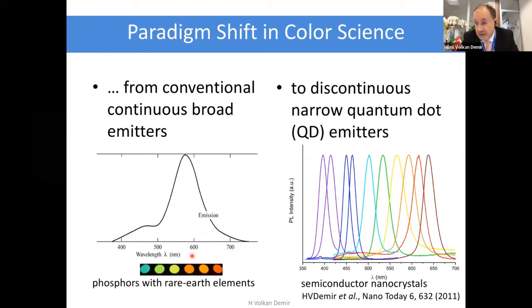The old common myth is that you generate the best color, for example, white, if you have broad emitters. So broad emitter, you can see one example here, which is well known, the so-called family of phosphors. This is really an alloy where you dope rare earth elements, and those are the emission centers. This is very nice, high efficiency, but the difficulty is to really control the emission characteristics. And it's very difficult to tune this emission like so.